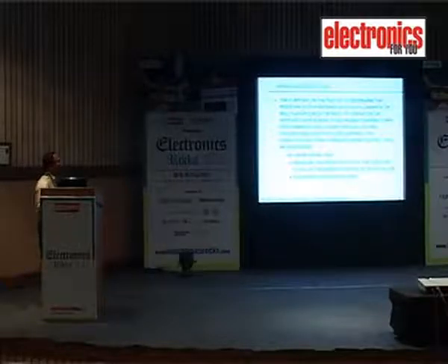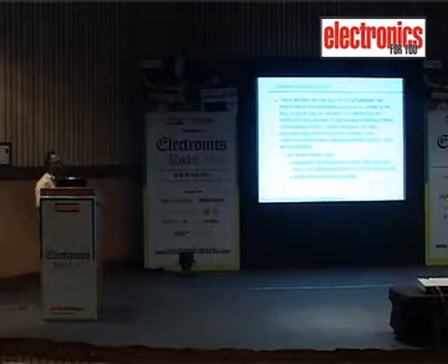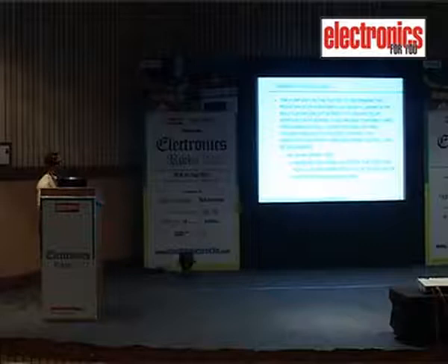Thermal shock cycling means we have to check the laminates we use, that is the base material we use to build up multilayer boards or double-sided boards. It will be repeatedly exposed to plus and minus temperatures, and we measure interconnection resistance prior to that test. After the thermal shock cycle, we should see that ICR should not change by more than 10% of the initial value. And further we do destructive checks like microsectioning, to see whether the barrel or the plated through hole is intact or not.